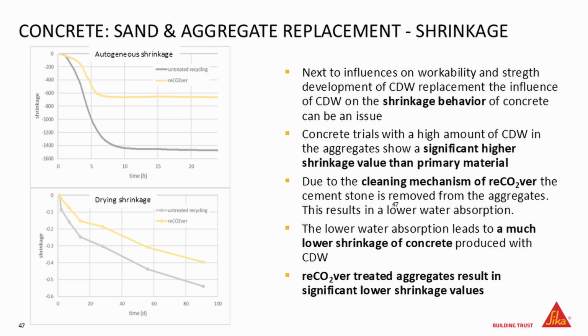So we measured two ways. And in both, we could see that when we replace the recycling aggregates with reCO2ver-treated aggregates, we could reduce the shrinkage significantly. And, of course, this then enhances the durability of the concrete. Because at the end of the day, when you have durability issues with your concrete, you need to replace it earlier, and from the whole lifetime perspective, that doesn't make sense. So this is a very important aspect as well when we are talking about recycling concrete.